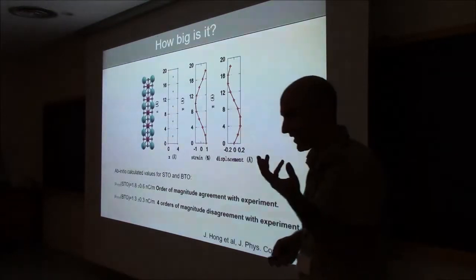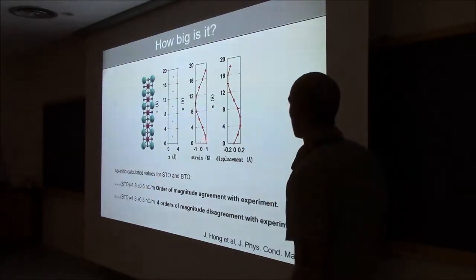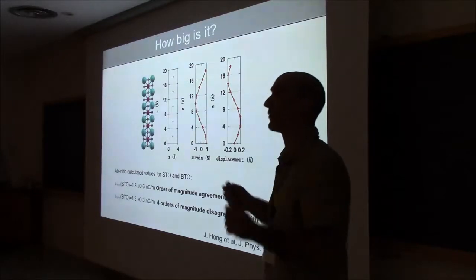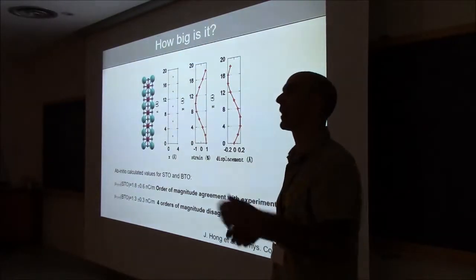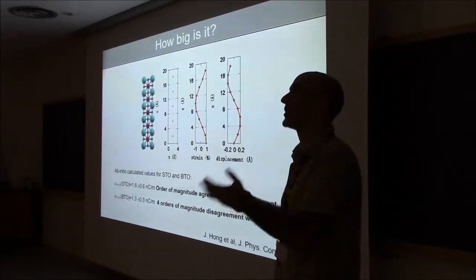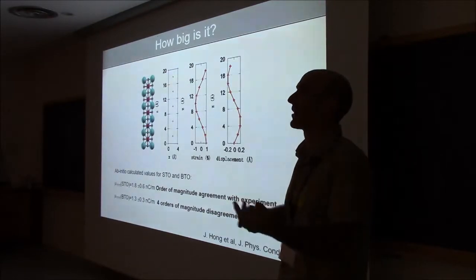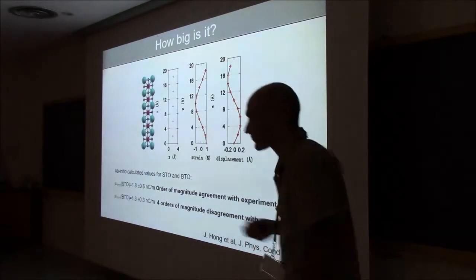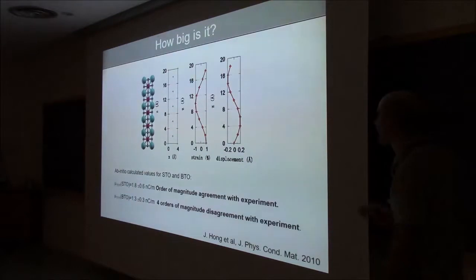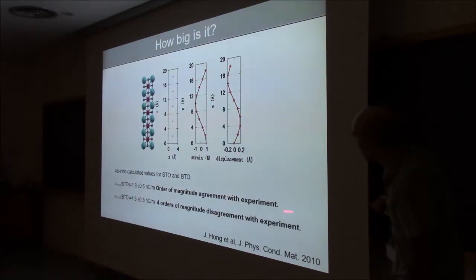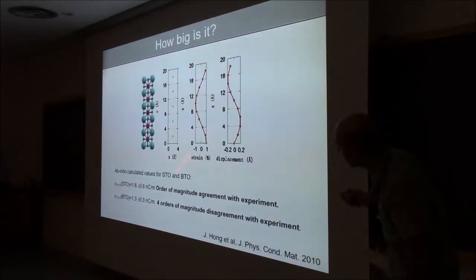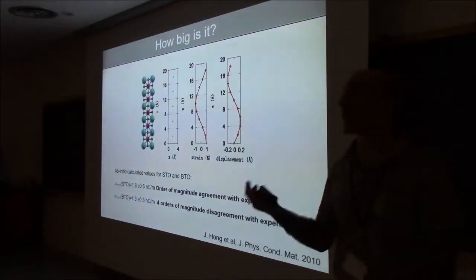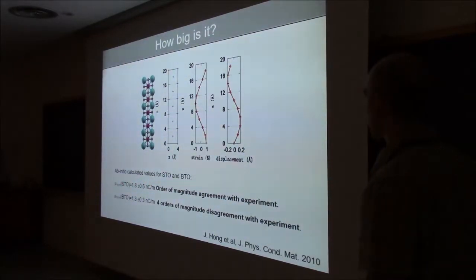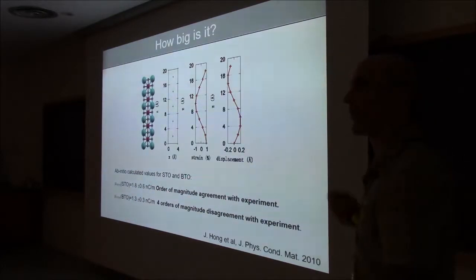This is a bit dodgy because basically, in order to induce this strain gradient, I have to clamp the position of some atoms and let the other ones relax. And which atoms I clamp and which atoms I let relax is a random choice. Okay, so it's not perfect. Nevertheless, this trick gave us a reasonable number for the flexoelectric coefficient of STO, which was of the order of a few nanocoulombs per meter, which matches the order of magnitude of our experiment.